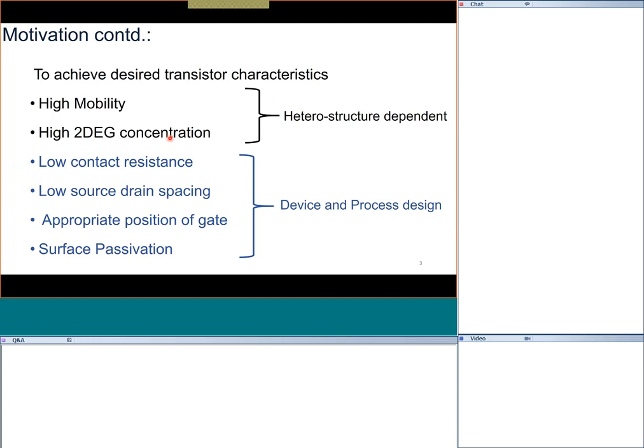A high electron density in the channel region allows larger current drive, and larger current drive means the device can handle higher power. We also need low contact resistance — for these very high power devices, I cannot over-emphasize its importance. The transistor action in a HEMT is actually simple, but the extreme conditions under which these transistors operate put a lot of restrictions on fabrication, and they must go through stringent qualifications to operate at very high performance without losing efficiency.